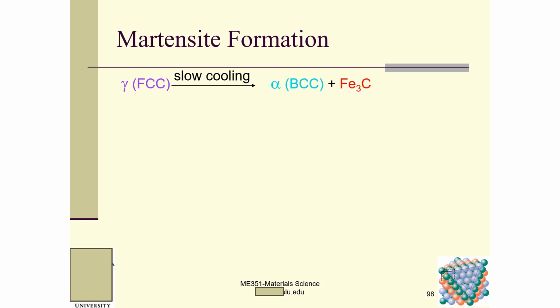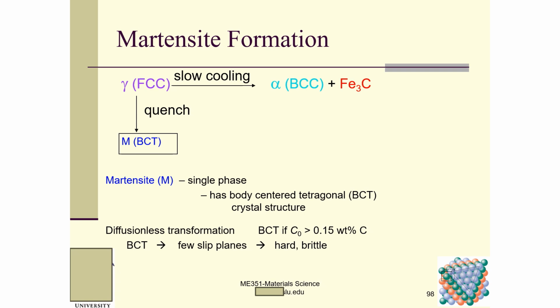For martensite formation, FCC with slow cooling gives us alpha and cementite. However, with quenching we get martensite, BCT, which is another crystal structure. Martensite is a single phase with a body-centered tetragonal BCT crystal structure, and it is diffusionless because of the short time. As a result, BCT has few slip planes, and it is hard and brittle. Martensitic material usually cannot be used as is because it is too hard. We need to temper it to get tempered martensite, which is more ductile than the original martensite, but still very, very hard.